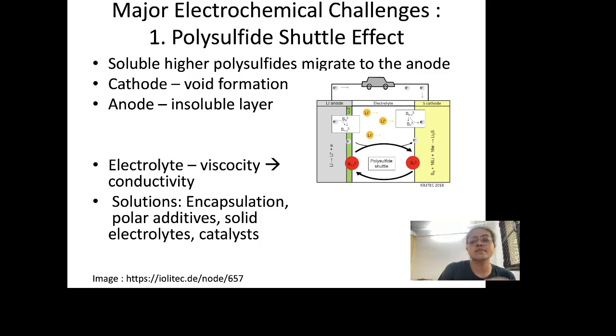But essentially there are problems that take place in each of the three segments, which is the anode segment, the electrolyte segment, and the cathode segment. The problem with the cathode segment is that the sulfur itself is getting reduced to these higher polysulfides and then getting dissolved into the electrolyte. It means that the active material of the electrode is now getting dissolved and is getting lost. Essentially there is loss of active material, and that leads to void formations in the cathode, and it leads to a reduced capacity because the active material is getting lost.